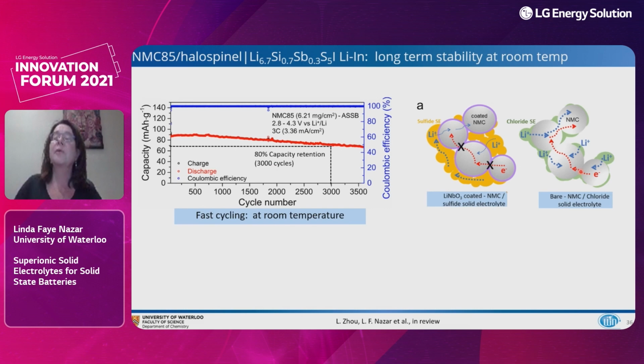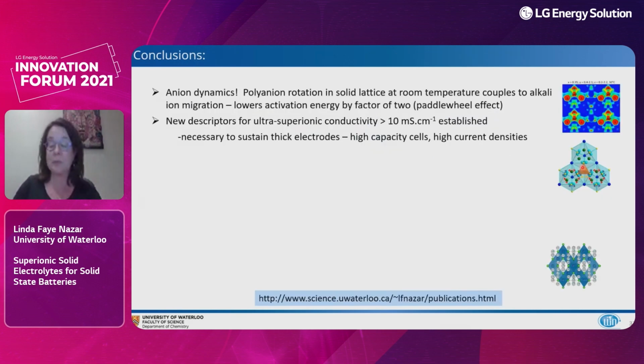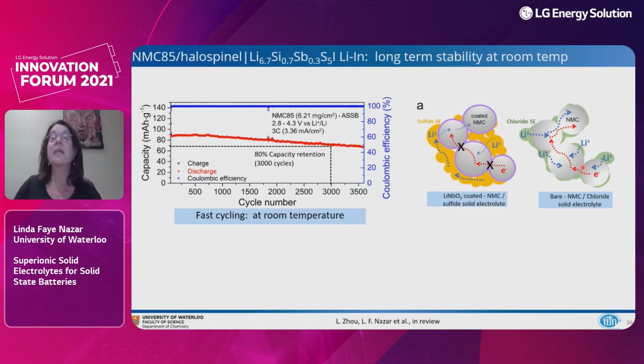This coating that we form is really kind of patchy, and so it's not in a matrix of the halide. We just simply have the halide coated in patchy particles, leaving some bare spots. And so that facilitates both electron and ion migration in the material.